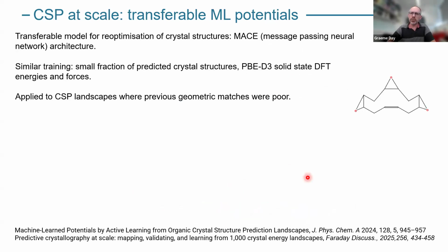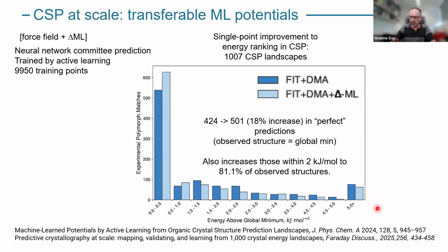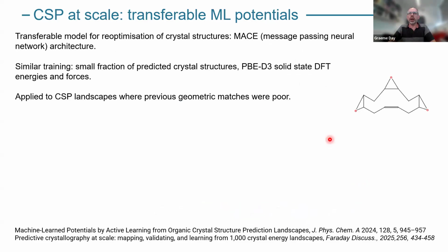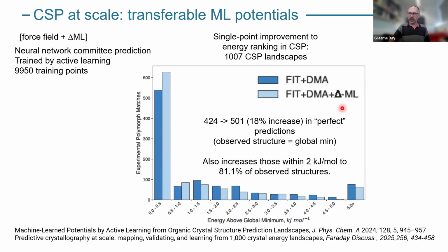Okay. Now we still have some structures here which are not predicted well. The observed structures are above 5 kilojoules per mole from the global energy minimum, so something's still going wrong with those. And what we saw in those was that they correspond to molecules where the molecule itself is a bit more flexible than most of the others. Okay, so when we applied this delta machine learning correction to our force field, it's not correcting the structure, it's just correcting the energy of a given structure.